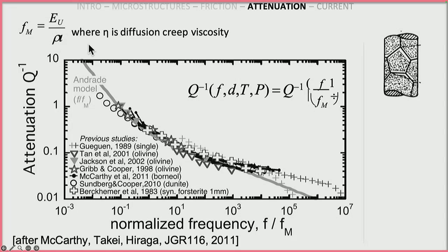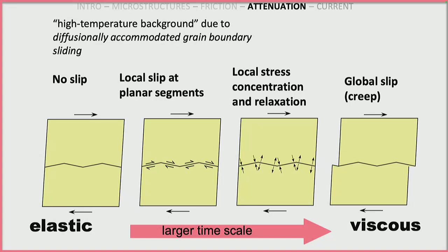Sorry, that got a little wonky, but normalized by the Maxwell frequency, all of these various data sets collapse to the same curve. This is fun. This is a universal response for materials that are pristine, as fabricated, tested in a very low stress environment. The consensus in the community is this mechanism. They all plot on the same curve, which means it's the same mechanism. And the consensus is that this is called diffusionally accommodated grain boundary sliding.